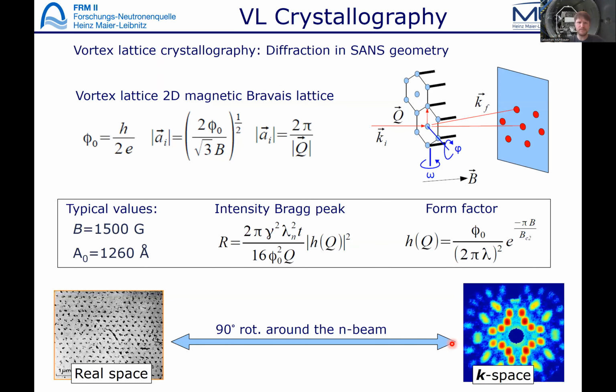And so how does it work? Well, a vortex lattice for a neutron is just a large-scale magnetic Bravais lattice. So these vortex lattices have Bravais properties, and therefore a vortex lattice can be seen as a diffraction grating for neutrons, very large scale, but essentially very simple. The setup is typically shown here. We have an incoming neutron beam, which is diffracted at the vortex lattice, and on the detector we see a diffraction pattern of our vortex lattice. So we see the picture of the vortex lattice not in real space, but in reciprocal space.